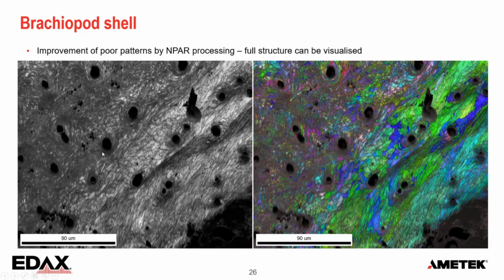And here on the top left, we can actually see the microstructure with these circular flat grains around those organic areas. And here on the right-hand side, you have the color coding as well. So it's not perfectly indexed, but it is enough to really get a good indication of the microstructure.